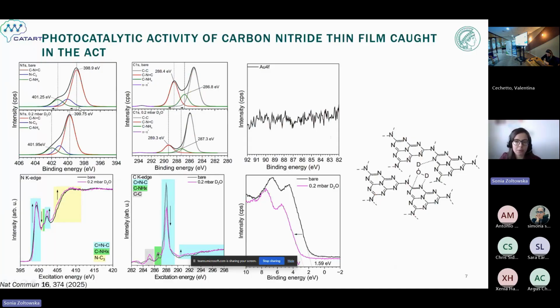We see those pronounced shifts, especially for the nitrogen features, also when we follow the NEXAFS spectra. But as a consequence of the donation of electron density to form the hydrogen bond with water, we also saw the shift of the valence band XPS position towards higher binding energy by around 1.04 electronvolts. In simple terms, we can say that the water participates in the formation of a joint new hybrid semiconductor structure with carbon nitride, which results in a different electronic structure than the one we know from the ultra-high vacuum conditions measurement. And this band shift, as we know, was never actually discussed before. And this is indeed the first step to activate artificial photosynthesis. And those are the electronic properties of carbon nitride which participate in the photocatalytic reaction.